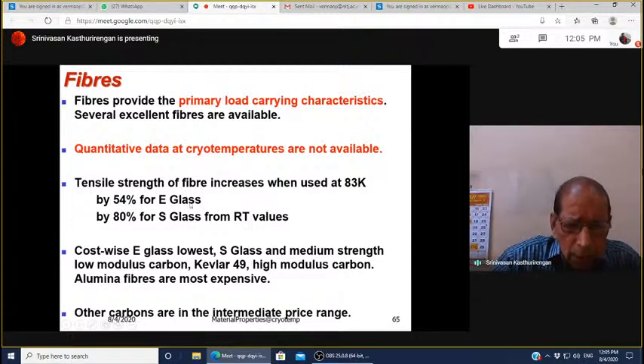If you take the tensile strength of a fiber, it increases when used at 83 Kelvin, or let's say liquid nitrogen temperatures. It improves by about 54% in the case of E glass, and it improves by about 80% in the case of S glass, from their room temperature values.